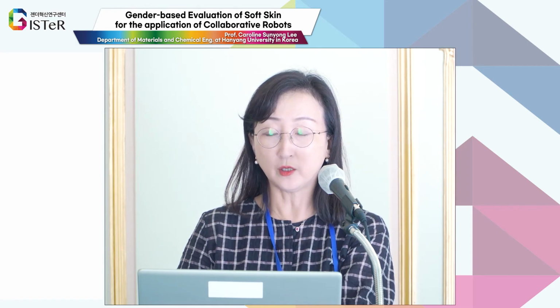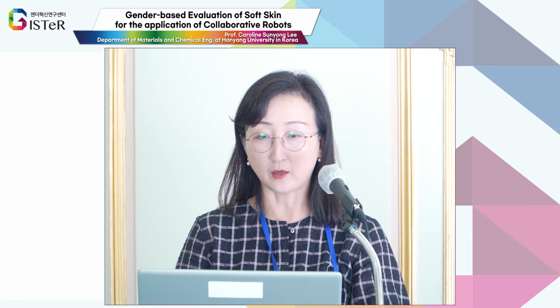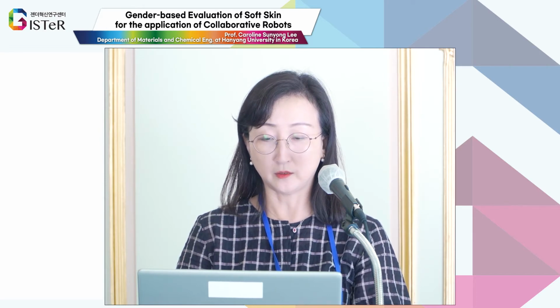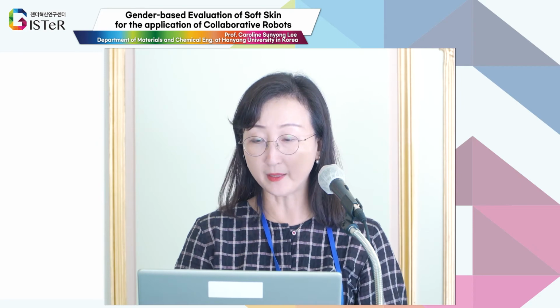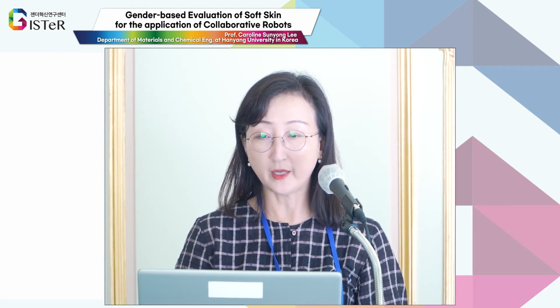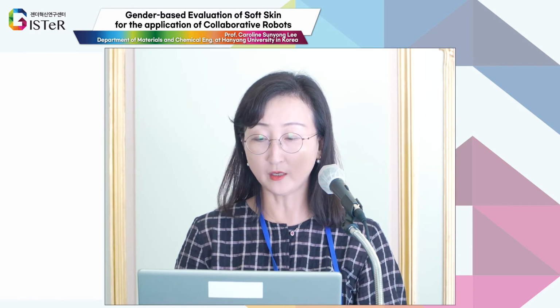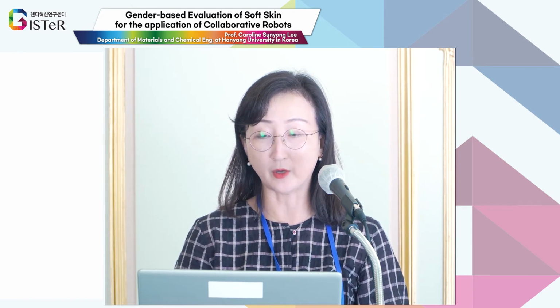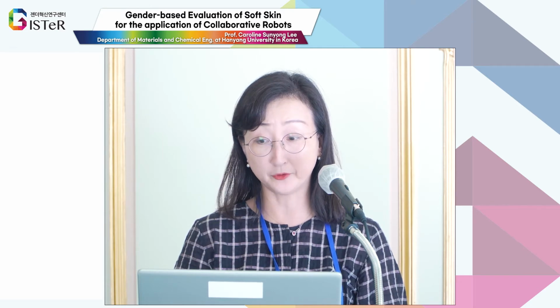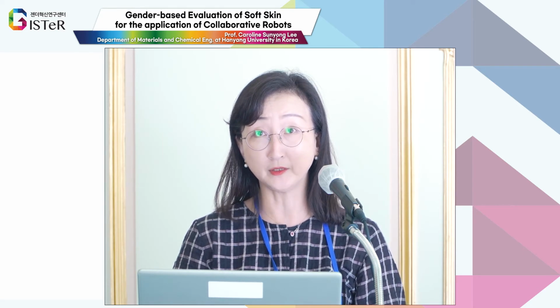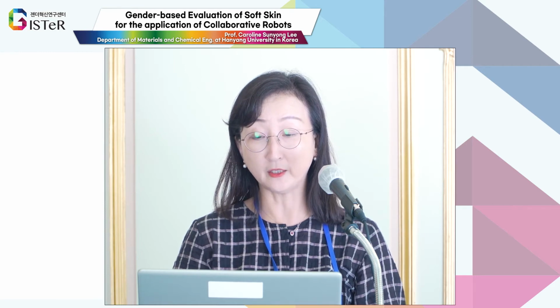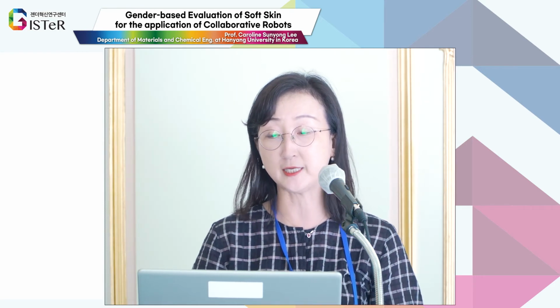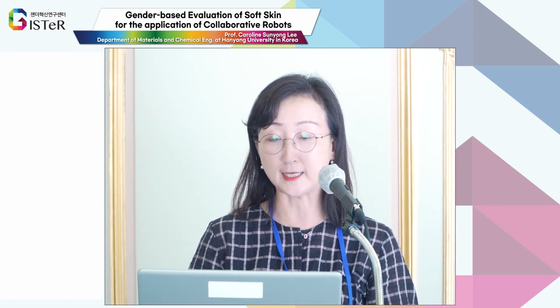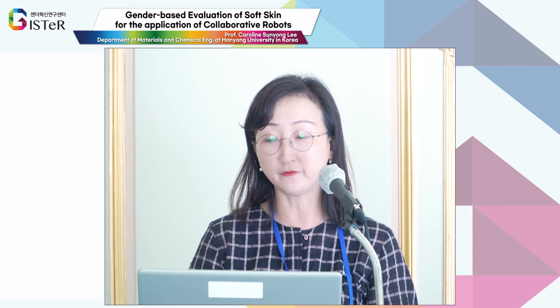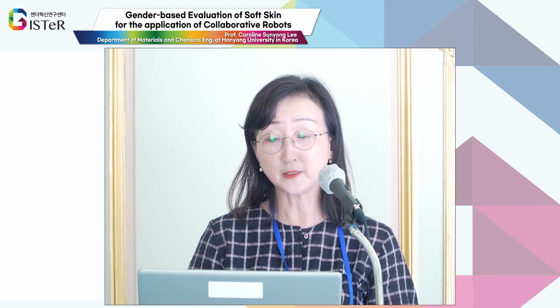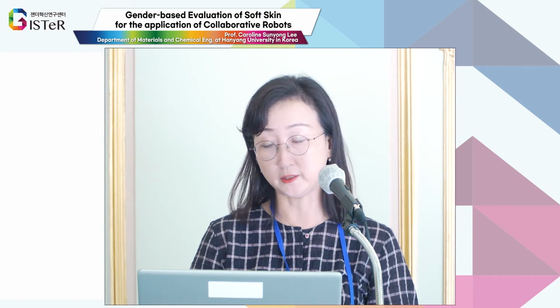So in order to relate this static survey to the scientific methods, we have used a contact angle test to relate to the stickiness. The contact angle test, as you can see here, measures the angle between the sample surface and a droplet on the sample surface. The higher the interfacial tension of the solid surface, the smaller the contact angle it gets. And the smaller the contact angle, the greater the hydrophilicity and adhesion it gets. Therefore, a sample with a small contact angle is considered sticky.